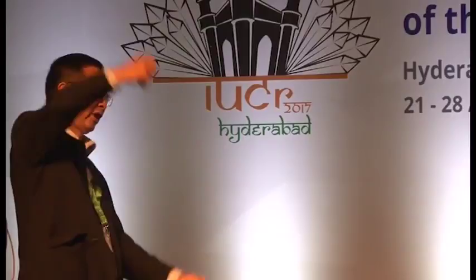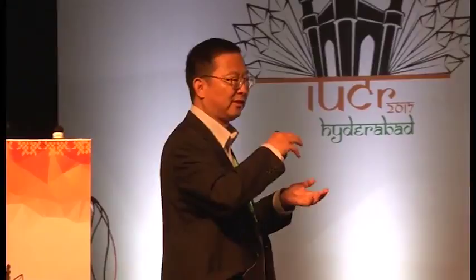We got quite big single crystals, and at room temperature, we can use a magnet to attract the crystals. It's not that the molecule is a single molecule magnet at room temperature. It's due to the quite big magnetic moment. The magnetic density is big enough, and it's paramagnetic even at room temperature. It's quite strong paramagnetic behavior, so the magnet can attract it.